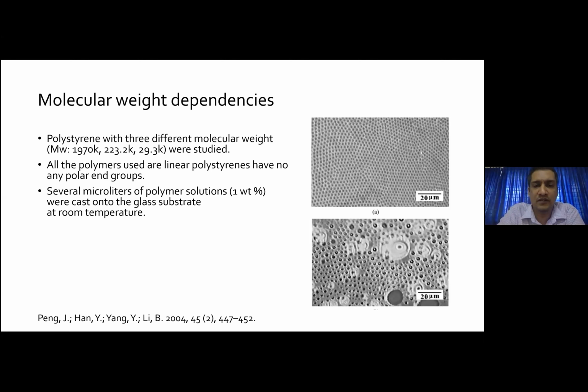So there is a threshold molecular weight because you need to have some kind of freedom for the polymer to move and reorganize. If the molecular weight is large enough, the high molecular weight polymer finds it difficult to reorganize and form the pattern. Then if you take a very small molecular weight, the movement will be too fast, and then you will have a non-uniform or uncontrolled breath figure formation. So there is an optimal molecular weight requirement for making a uniform and controlled pore size in the case of thin film breath figures.